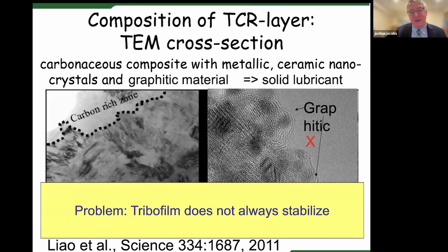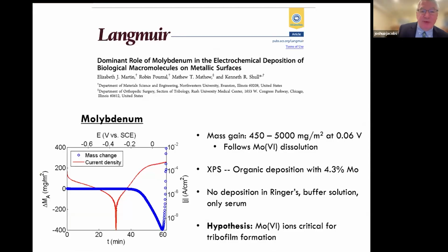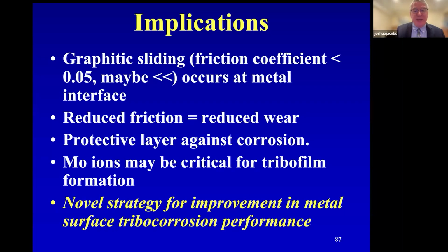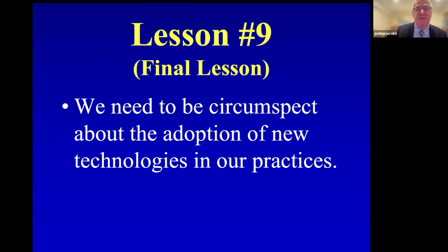So if we could come up with strategies to stabilize this tribofilm, this might be a way to minimize the amount of debris generation. And through other studies using, for example, quartz crystal microscopy, molybdenum, which is an alloying agent here, may be essential to form this tribochemical reaction layer. So the implication of this is that there can be novel strategies to improve metal surface tribocorrosion performance. So metal-on-metal bearings may be used in the future to take advantage of their benefits. But right now, the way we stand is that we really have struggled with dealing with the biological consequences of the metal debris released from these devices.